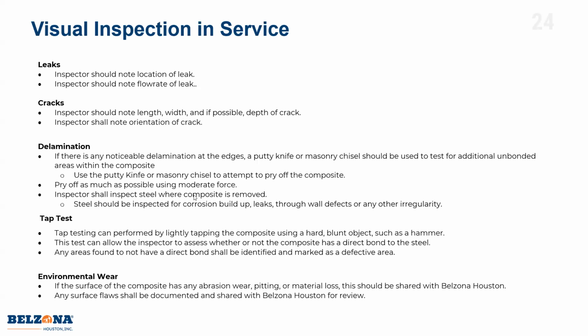You can do a tap test. You lightly tap the composite with something like a hammer, and the sound is more of a ding when it's bonded to the steel. It's almost like you're hitting the steel, and if it's not bonded to the steel, it sounds very hollow. So a tap test is a great test. You do that after installation and during your inspections, to make sure the composite is bonded to the steel. Then check for environmental wear. Make sure there's nothing on the surface. Maybe some acid has been spilling on it, because you could be wrapping a pipe in a secondary containment for sulfuric acid, and it could have had acid spilling on it for a couple of years. You never know what the scenario is, but there are a lot of things to look for in your visual inspection.